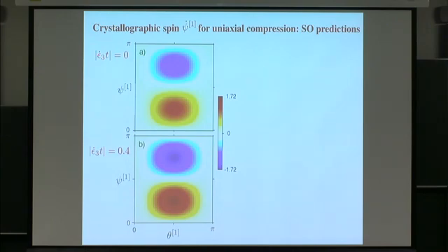So what you see is that at the initial instant, when the texture is isotropic, and you calculate the instantaneous spin at that time, you get a function that looks like this. Then you run the model a bit further to a strain that's higher, and you get a spin that looks like this. Well, they look like the same function. This is very surprising, and it turns out they are the same function. So the observation is that psi dot 1 is equal to this combination of trigonometric functions, very simple.